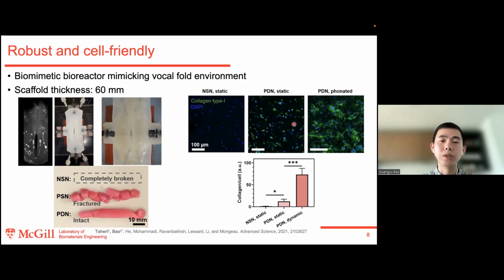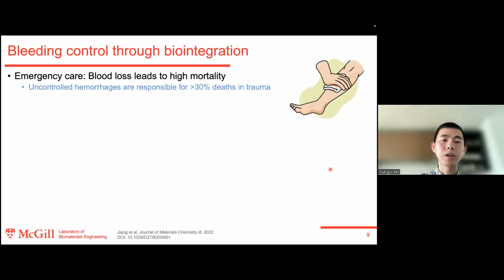And with the help of biomimetic mechanical stimulation, the vocal fold fibroblasts we encapsulated within the scaffold even secrete much more collagen compared to the other two situations, which means that our porous and tough hydrogel could potentially improve the therapeutic outcome. And after the fabrication, the next step is the integration.